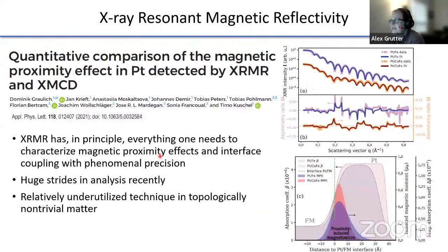The other thing I think is going to have a really big impact is X-ray resonant magnetic reflectivity. Here I'm just throwing up a really quick example from Timo Kuschel's group, where they take advantage of the really high intensity X-rays and the sensitivity to different elements to do really high precision measurements on proximity induced magnetization of platinum next to cobalt or iron. So this has traditionally been extremely hard to analyze, but it's been getting a lot easier. I think it's somewhat underutilized currently, although maybe people are doing things I haven't seen yet in topologically non-trivial materials.